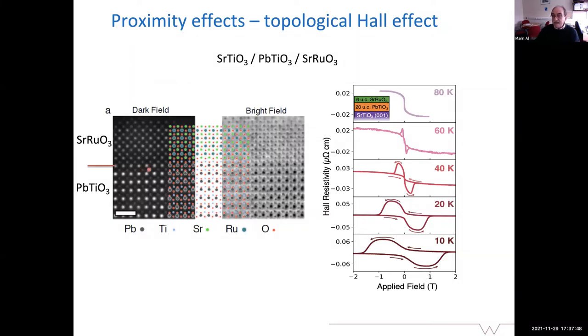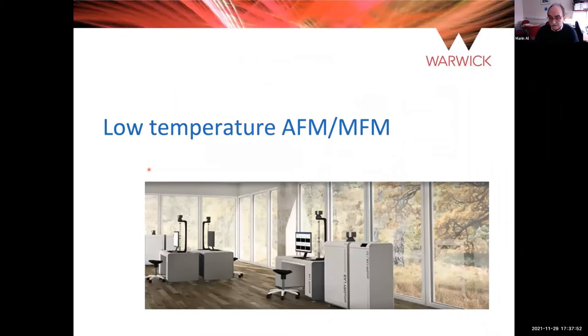And we also have a very nice tool, which is a low temperature atomic force microscope, which can do all kinds of microscopy, like room temperature atomic force microscopy, which includes magnetic force microscopy, piezo force microscopy, scanning Kelvin probe microscopy, and so on and so forth. We can do it down to 1.5 Kelvin, and we can do it with a vector magnetic field, which has 9 Tesla axial and 1 by 1 Tesla in plane. So we can put our field in any direction up to 1 Tesla, which is sufficient for most of the, let's say, relatively soft magnetic materials.